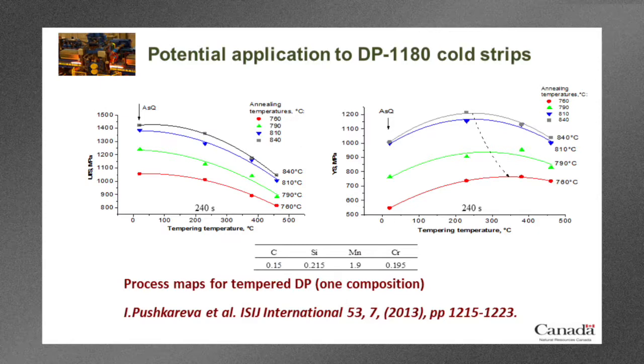On this graph here, on the left-hand side, we're plotting ultimate tensile strength as a function of tempering temperature. Here there are 4 different intercritical annealing temperatures that were studied. The 760 degrees C is on the red curve here. The green curve is 790. The blue curve is 810, and the grey curve is 840.